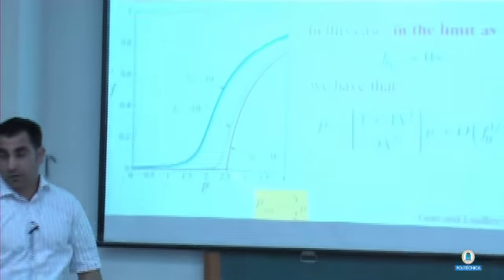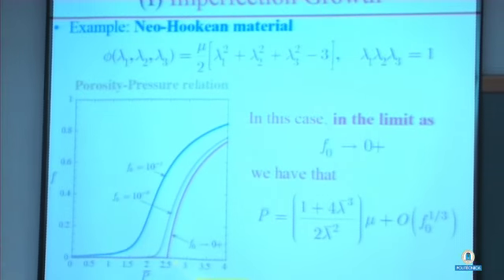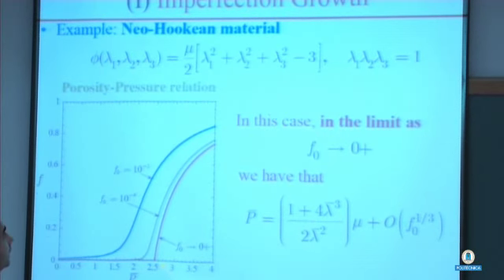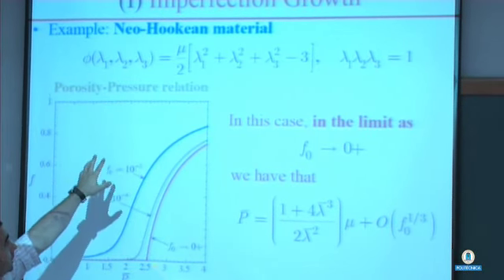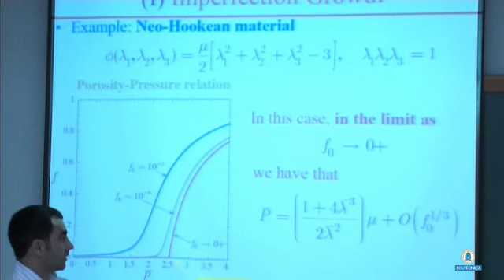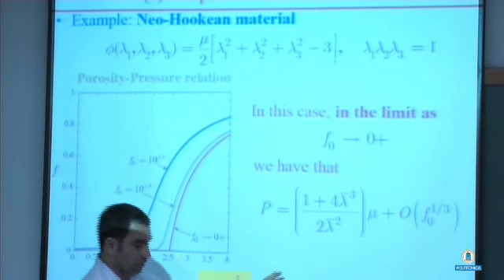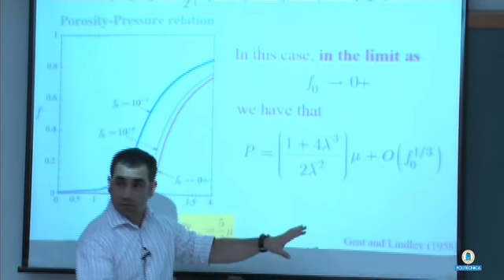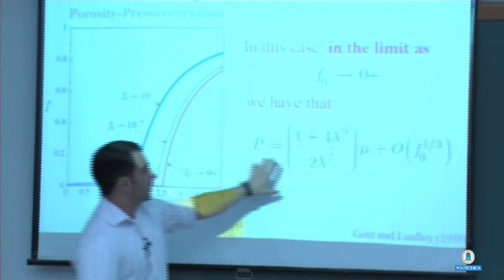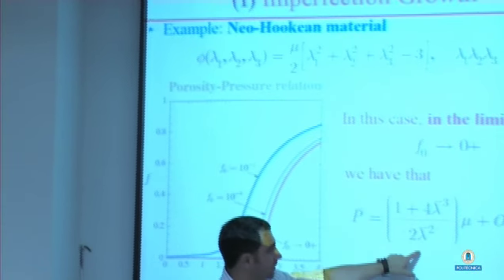Now, let me show you that in the context of a particular potential. The formula applies for any potential, but let me show you this classical Neo-Hookean, right? So this is probably the simplest valid model for a rubber. And so that's the potential. You can put it in the integral. In that case, the integral can be done analytically, and if you do the integral, take the limit of F0 goes to 0, the linear term in the pressure goes like this term.